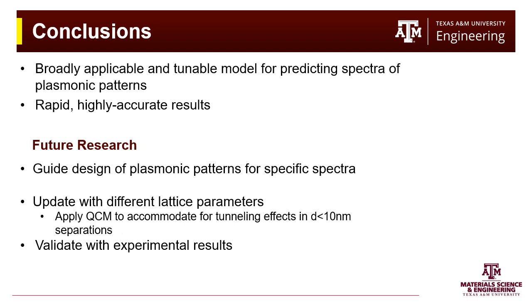Another update that I would like to see accomplished would be updating this same exact model, but with various different lattice parameters, and even applying a quantum corrected model to accommodate for tunneling effects, as those lattice constants and separation between various plasmonic bodies reduce to beneath about 10 nanometers. Tunneling effects, non-locality effects start to take place, and seeing this be accommodated for and potentially modeled and utilized to design certain spectra would be quite the interesting use of such a platform.